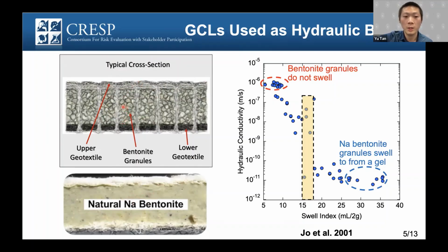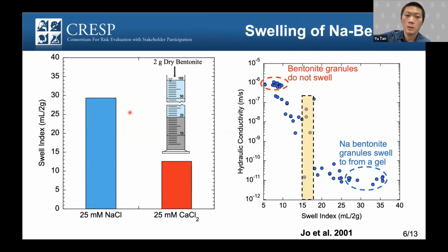But if the granular bentonite is hydrated in calcium-rich solutions, the bentonite granules do not swell. So you can imagine that if we pour water at the top and it flows through the GCL, if the granular bentonite is not swelling, like these sand particles, the solution will flow through the space between the granules and yield high hydraulic conductivity. So it's not able to work as a hydraulic barrier. As we mentioned, the key factor for the performance of GCL is the transformation of the granular bentonite into the gel structure, so it depends on the swelling of bentonite.